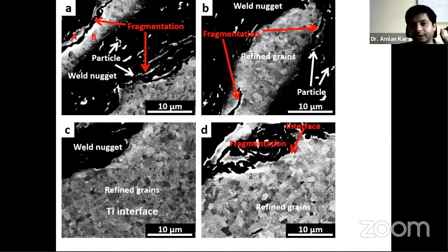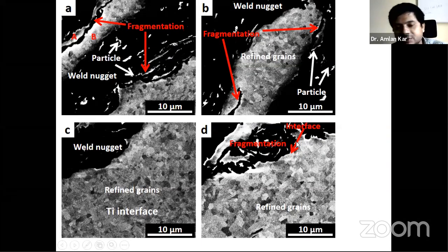The adiabatic shear band also promotes the formation of voids, and when during the deformation these voids connect to each other, there is a possibility of formation of particles. The same thing we can see here: there is a formation of voids, and when they connect, it forms a crack. During the deformation, that crack developed further along the shear deformation direction, and that led to the formation of particles. You can see this particle is actually formed from these locations. And similarly, this is another location you can see. This is the shear band driven fracture.